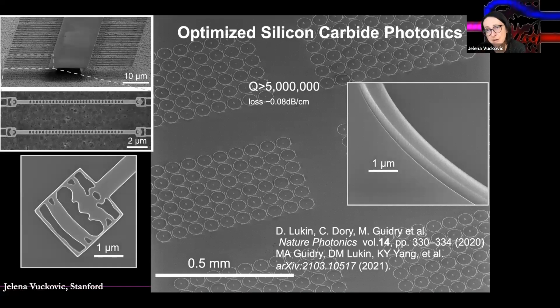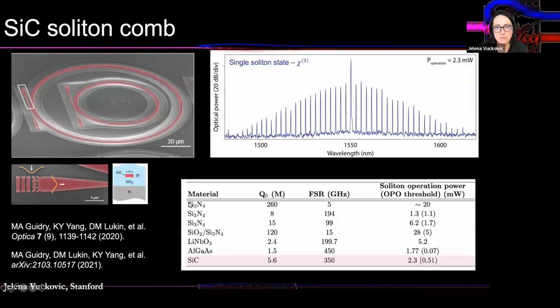So it's actually even better than silicon photonics, which is kind of state-of-the-art photonics that is done in the foundry. This one actually has even lower loss than silicon photonics. And what is also very important is that once you have silicon carbide on insulator, the process for fabrication is exactly the same as for silicon. So that's quite exciting and it also hosts very high quality color centers. So again, here is our silicon carbide photonics with very high quality. It has very high Q factors. It's also very interesting for nonlinear optics. You can demonstrate high Q factors. You can put inverse design structures.